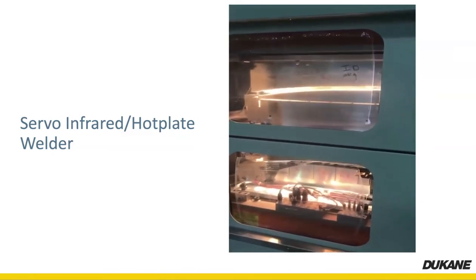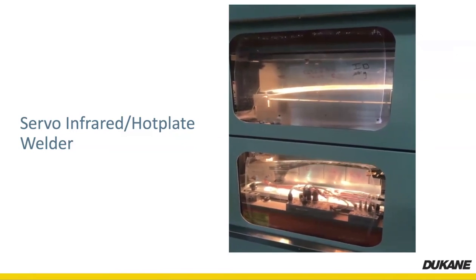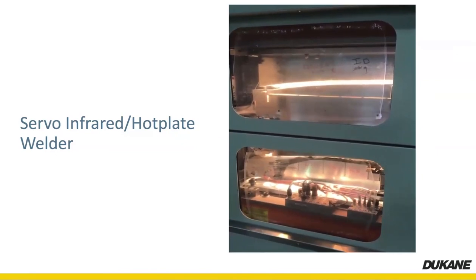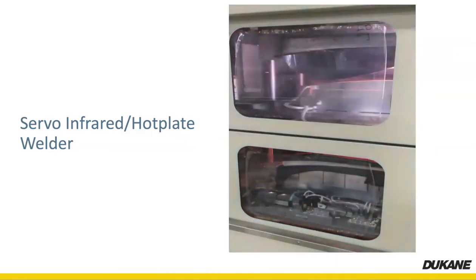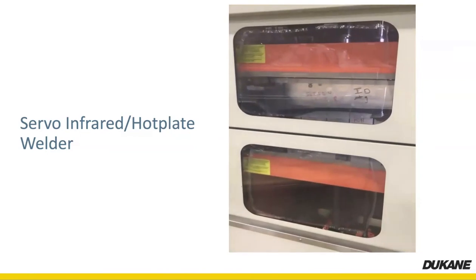Now, I want you to think about what you're seeing here going forward in the presentation. You're seeing a little smoke, and that does happen quite often in infrared welding. And that's one of the drawbacks. In a lot of cases, it's not a problem, but sometimes to get the full depth of penetration that we need, we burn the surface a little bit. And in clear parts, maybe we get a little discoloration, and sometimes maybe a little reduction in strength, to be completely transparent. But in most applications, it's not a problem. And if it is, we have other technologies that solve these issues going forward.